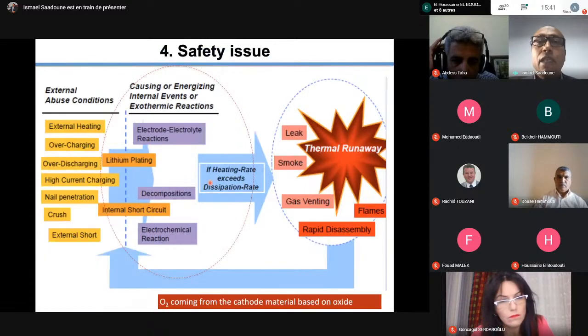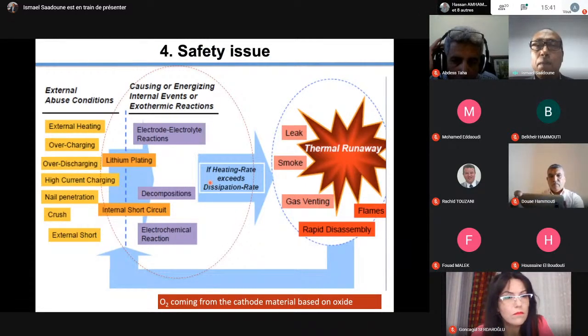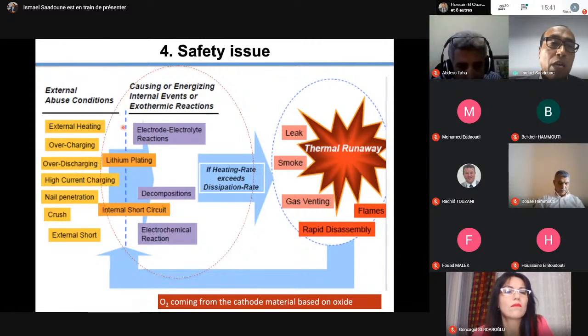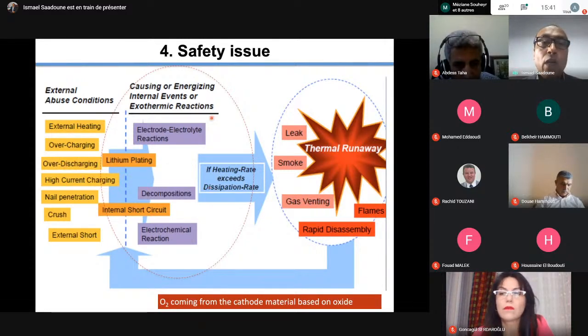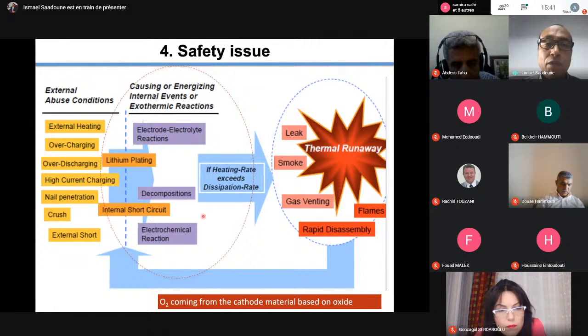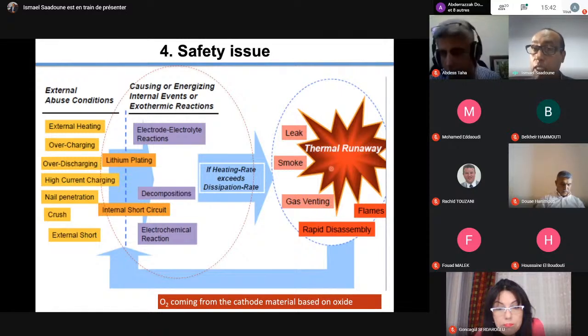Just very fast, what causes this safety issue? We can have some external abuse conditions like external heating, overcharging, over-discharging, high current charging, or so on. We can have some internal events inside the cell, like electrode-electrolyte reactions, decomposition, or side reactions. We can have lithium plating and internal short circuit. If this phenomenon occurs and we are heating, we can get explosion, smoke, leak, gas venting and flame in the cell, and we can see what happened.